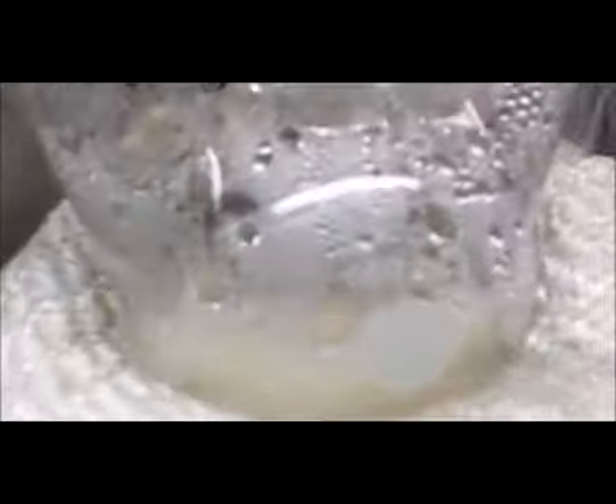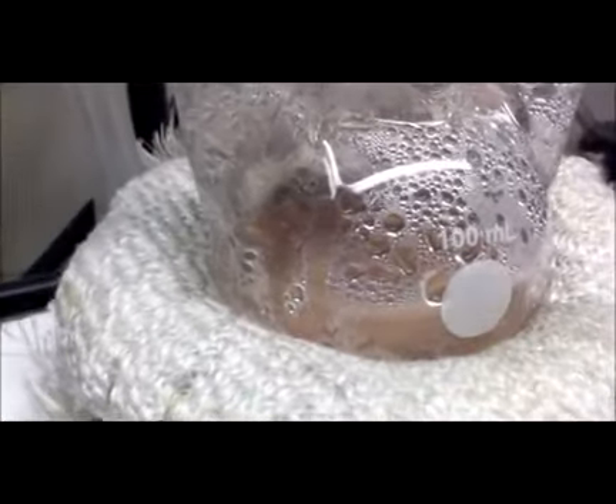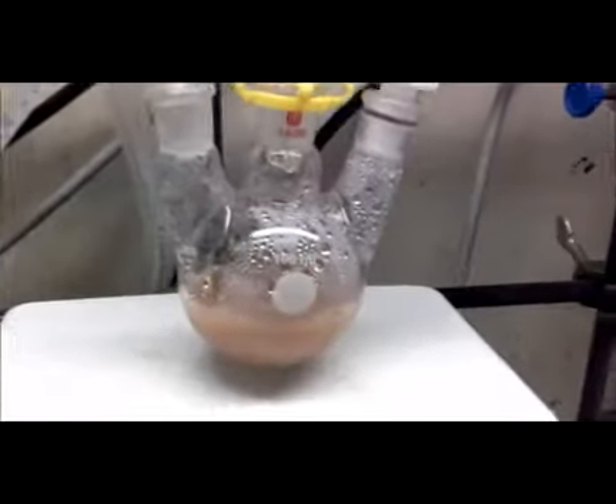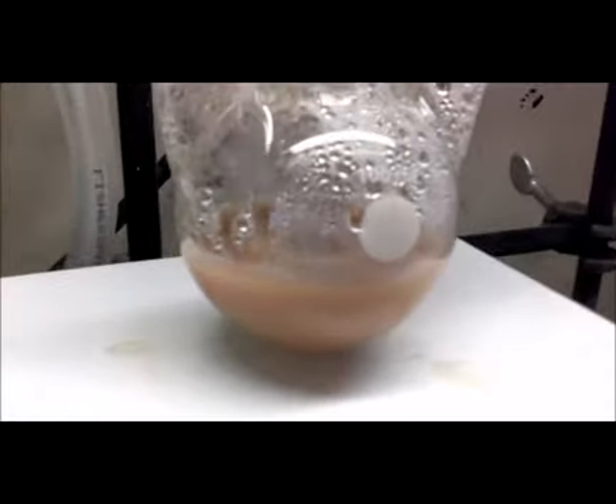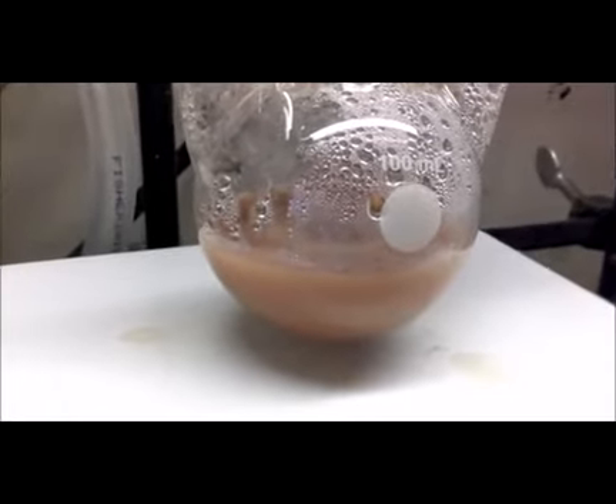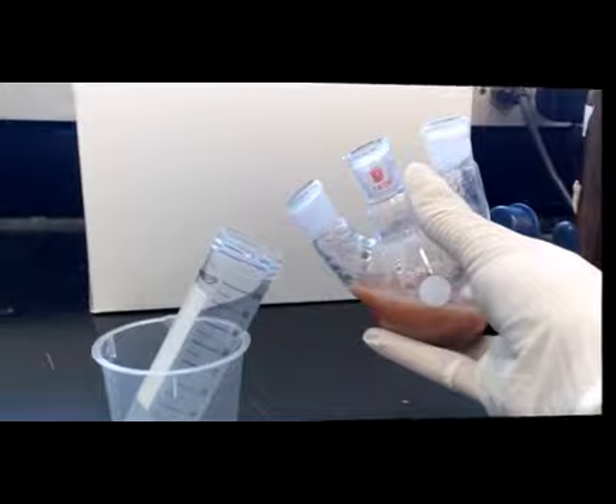After a few minutes of heating, we can see the color has changed to a pale orange. As it continues heating, we can see the solution turn a darker orange. After the time is up, we can see that it has become a very deep brown-orange color, and we let it cool and do 3 washes with water and place it in the vacuum to dry.